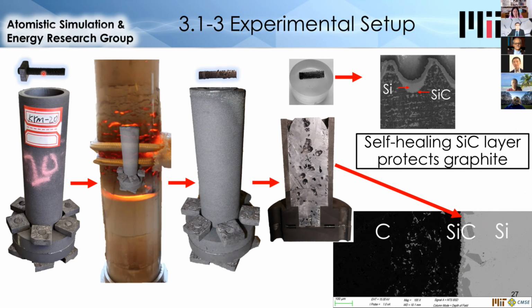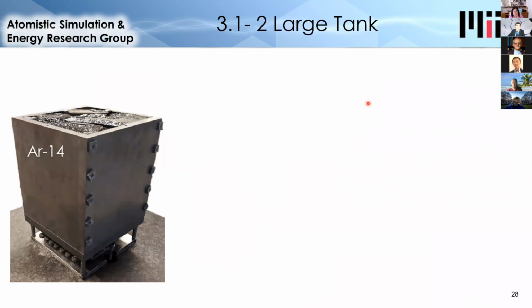In these tests, I also put a bolt in the silicon in order to determine if it could survive the contact, because the full-scale system has bolts on the inside and the outside of the tank. And the bolt also formed a silicon carbide layer and didn't exhibit any strength loss.